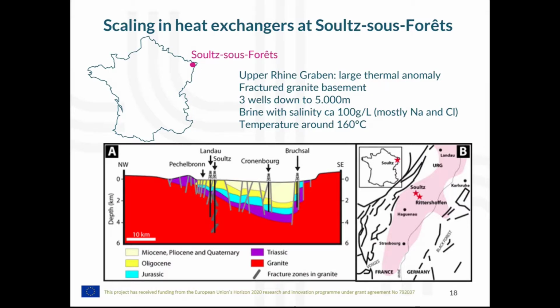Thank you. So we are going to focus now on the scaling phenomenon in the heat exchangers at Soultz-sous-Forêts. Soultz is located in the upper Rhinegraben in eastern France, and the granite is harnessed at a depth between 4 and 5 kilometers. There we find brine with a high salinity, around 100 grams per liter, containing mostly sodium and chlorine, and with a temperature around 160 degrees centigrade.